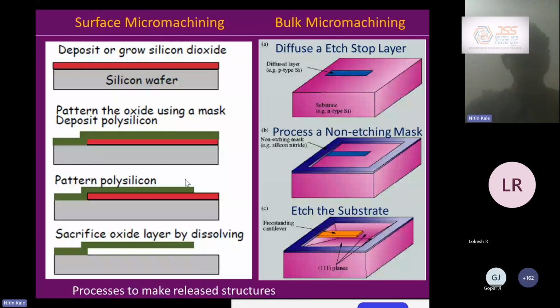I also mentioned that I'll talk about surface micromachining and bulk micromachining. In a surface micromachined device, you basically have a sacrificial layer. Here is an example. You start with a silicon wafer, you deposit an oxide, and then you deposit, let us say, another material, which is, say, polysilicon. You pattern it. Now, you want this polysilicon to be a movable structure. So you put it in an etchant of silicon dioxide. Now this silicon dioxide gets removed and this polysilicon is now movable. So it can, for example, vibrate. It's a cantilever. That's the MEMS part.